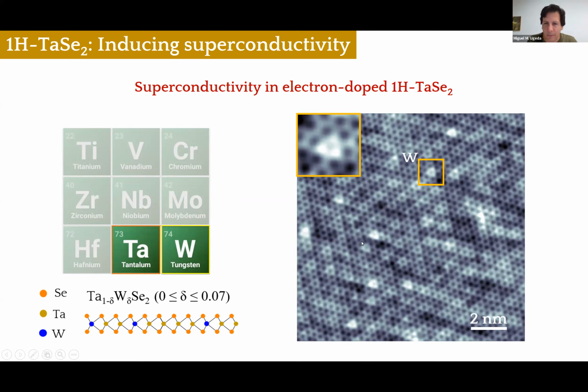In particular, these two black triangles are pointing in the opposite directions to the bright triangles. So the fact that they are pointing in the opposite direction means that whatever it is, that defect is not a substitutional tantalum atom, right? Because otherwise it should be oriented towards one of the directions, it cannot point in two directions. Do you follow me? Yes. So probably the black ones are, I don't know what kind of defects, selenium vacancies, tantalum vacancies, I don't know, but